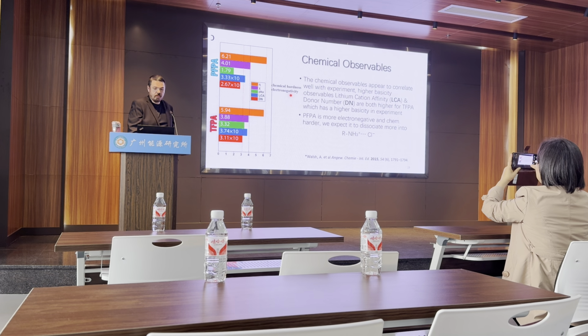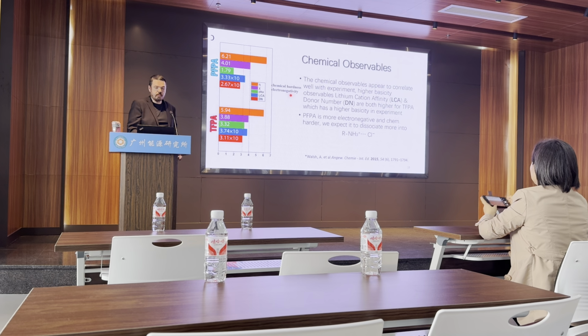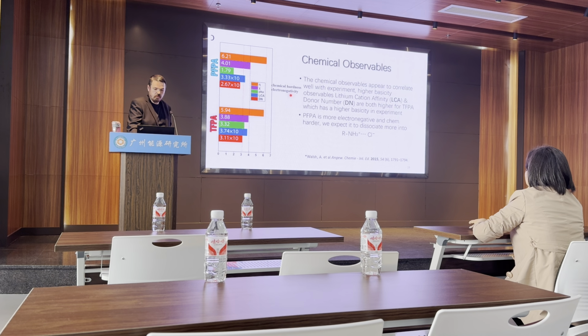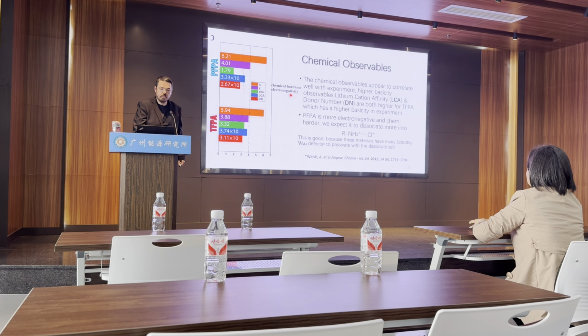So we know that PFPA is more electronegative and chemically harder, so we expect it to dissociate more and thus be more available to passivate the surface. So that's probably one of the reasons why it's somewhat better. And this is good because we have many Schottky defects to passivate, and this is the big paper.